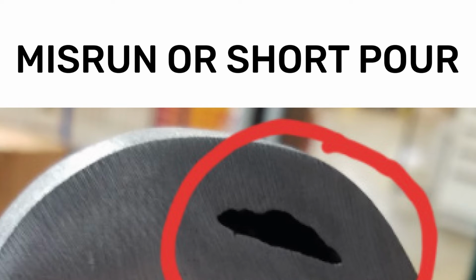And then for misruns, these happen when you take the casting out of the mold and part of it's missing. So the metal just didn't completely fill the mold and you have a hole or a gap in the part. This could be a design issue too. For example, if your walls are too thin, the metal is going to solidify before it can completely fill the mold. In permanent mold casting, you're using that gravity tilt pour that we talked about earlier to fill the mold, so we recommend at least a 0.18 inch wall thickness to make sure that the metal fills the entire mold